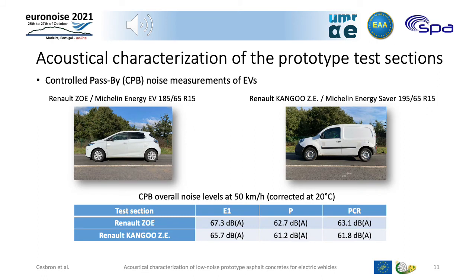Controlled pass-by noise measurements have also been performed for 2 electric vehicle models. The microphone was located on the left-hand side of the vehicle at 7.5 meters from the middle of the test section and 1.5 meters above the road surface. As you can see on the left, the first configuration was a Renault Zoe fitted with Michelin Energy EV tires, and as you can see on the right, the second electric vehicle tested was a Renault Kangoo ZE fitted with Michelin Energy Saver tires.